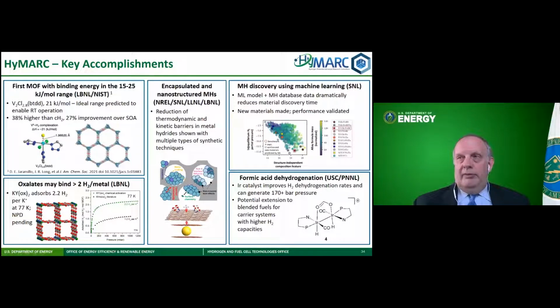And again, just for a matter of time, another exciting development. This is actually one of the seedling projects, University of Southern California, working with PNNL, have shown an iridium catalyst for the decomposition of formic acid, where they can get very high rates, but also directly generate over 170 bar pressure from the decomposition of formic acid. So this could be a big advantage in applications where you need higher pressure, because you could eliminate some of the compression stages to reduce the cost of compression.